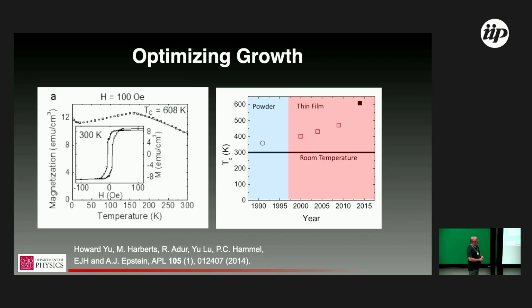And then on the right, just using that transition temperature as a crude metric of materials quality, you can see that starting from the solution synthesis, which gives you a powder, then transitioning to CVD, that first open square is the previous slide, and then progressively optimizing the material from a thin film growth perspective, you can get significant improvement in homogeneity and materials quality. And so this has been one view of the trajectory of this system.